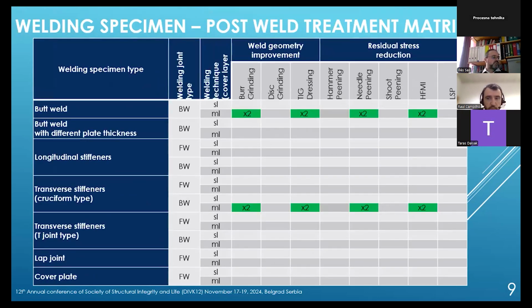Based on this, we developed the welding specimen post-weld treatment matrix for further investigation, where you can see the specimen type, welding joint type, the layer techniques, and also the weld geometry improvement and residual stress reduction methods. You see some green dots here. That is our actual scope of investigation, to start to compare the effect of the different post-weld treatment methods in selected weld specimen types.